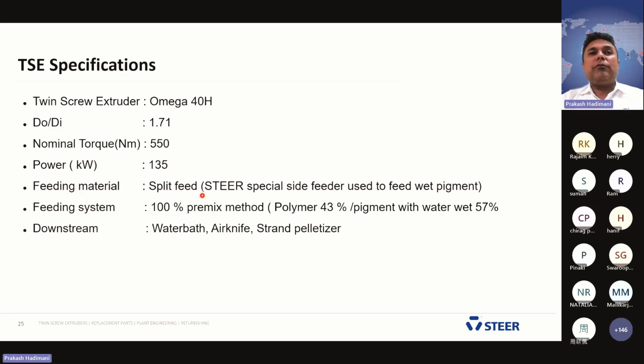For the feeding material, we used a special feeding mechanism to feed the wet pigments. In the feeding system, all 100% is premixed with the polymer. Polymer is 43%, and the pigment with the water is almost 57%. And we used a downstream water bath, air knife, and the pelletizing system.